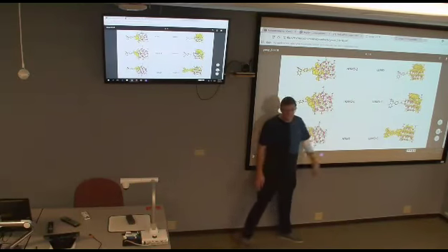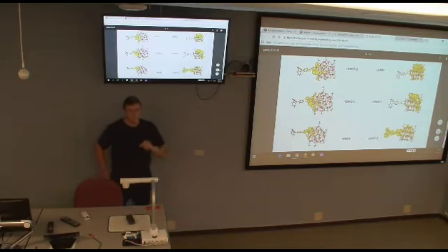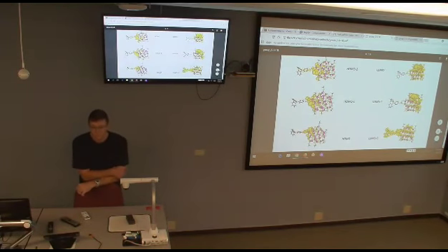So your HOMO-LUMO transition is probably not very optically active, not huge. But you have, let's say, maybe HOMO-5 to LUMO and LUMO+1, and probably those states will have more character of the quantum dot. But this is for both systems, independent of the linkage. They all behave pretty much the same.